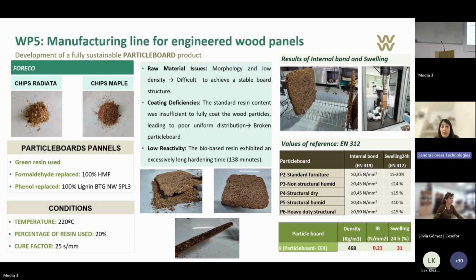This was because of the low density and morphology of the specific wood chips used. To improve these particle boards, we increased the percentage of resin and the curing time. These adjustments ensured the wood chips were fully coated with resin, compensating for the low reactivity of the resin and these technical limitations. Characterization was carried out, but unfortunately the panels did not reach the standard value, as you can see in the internal bond table.